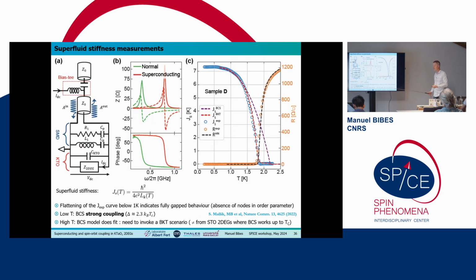We are currently trying to make more experiments to try to get more insight into the superconducting states. These are some superfluid stiffness measurements from our collaborators, Nicolas Berjal at the SPCI. Here we measure the kinetic impedance of the superconductor across the transition, and we determine the superfluid stiffness, which we can then plot as a function of temperature.